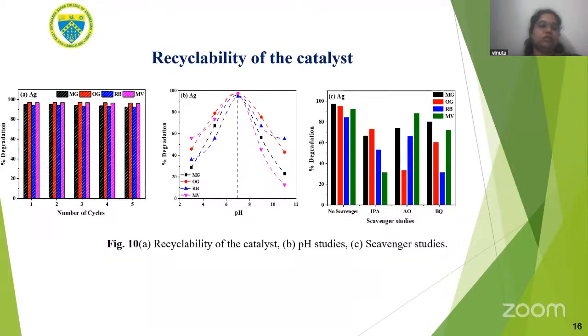So as shown in the figures, the results of the photodegradation experiments evaluate the catalyst reusability. After each cycle, the catalyst was successfully recovered and filtered with the help of Whatman filter paper, and we used it for the next cycle. Therefore, we have used the same catalyst for 5 consecutive cycles without significant loss of efficiency. Hence, it shows the recyclability of the catalyst. That means we can use the catalyst for a number of cycles.